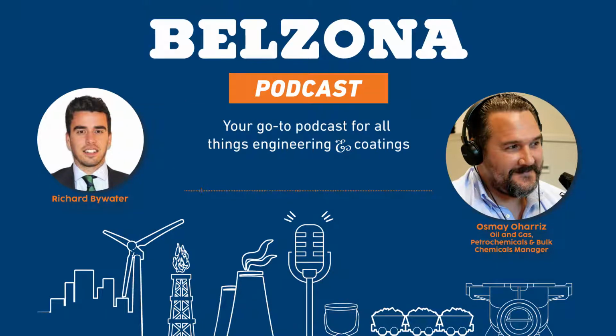So steamout is a purging process that employs pressurized steam at temperatures traditionally closer to or above 200 degrees C, which is roughly 390 degrees Fahrenheit, for as long as 24 hours. Although you might actually see longer than that recently. Yeah. I've seen several industries, they employ about 48 hours. It might change depending on where you are.